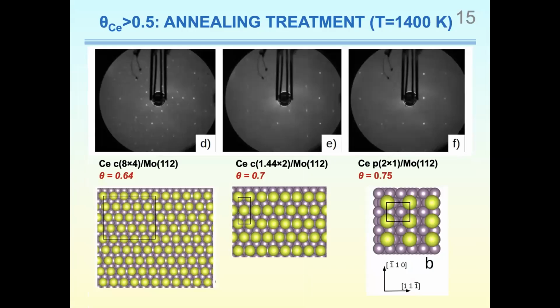Annealing in the range of coverage from 0.5 to 0.75 resulted in significant changes both in surface structure and the work function. Instead of the primitive 2x1 structure, new adatom arrangements appear, showing a denser compression inside the furrows. Here you can see LEED patterns which are attributed to incommensurate centered 8x4 and centered 1.44x2 lattices with stoichiometric coverages of 0.625 and 0.7 respectively. Suggested hard sphere models of the corresponding submonolayer structures are shown below.